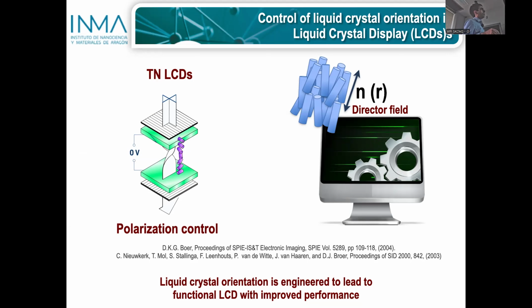at the glass surfaces, in a perpendicular fashion on each of the surfaces. The elastic energy does the work to generate these twists, and by applying an electric field in each of the pixels, you can reorient the liquid crystal and therefore change the optical properties of the system and play with the polarization, and in this way build the electro-optical valve that is in each pixel of your display.